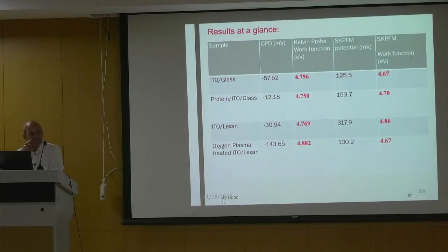Why I am stressing this point is, generally when you send this manuscript to a publication, the reviewer says both are surface work functions, explain the difference, and you try to correlate. It can't be done because two techniques are different, two areas are different, two methods are different. And from this change in work function from SKPFM, you may not be able to get the quantification data as you get in Kelvin probe. Make it a very important point.